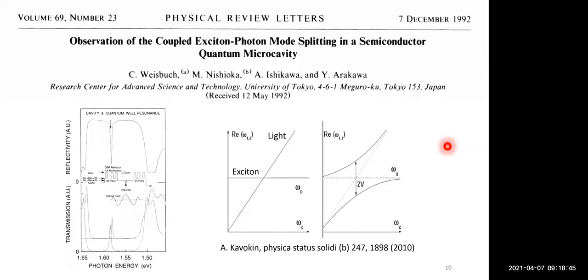So part of this issue has been solved by using organic materials and wide bandgap semiconductors, if you think about gallium nitride or zinc oxide. But even in some of these cases, for example in the organic systems, they exhibit strong localization effects because of the disordered potential landscape. And even if you consider the wide bandgap semiconductors, they are basically restricted to the shorter wavelength range, and they also require quite sophisticated lattice matched growth techniques.